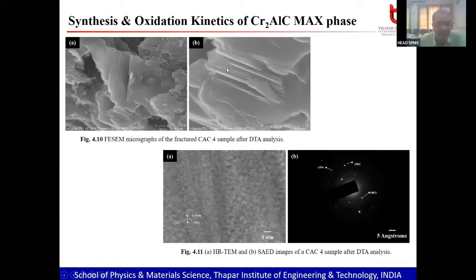You know that this is the layered structure. If you can see the microstructure of these synthesized mixed phases, you will find that it is existing in the form of a layered structure here. This is the same FESEM image, and this interconnected layered structure is very, very important here. Through lattice fringing measurement also we could confirm that this is the MAX phase here. A lot of work has been done.